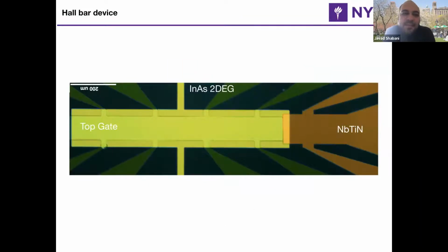So then this is sort of an optical image of the device. There is a hall bar on the left side. There is a niobium titanium nitride on the right side. And you can basically send current from left to right, measure hall data or across the interface. The dimension is large, right? So the width of this hall bar is around 150 micron, right?